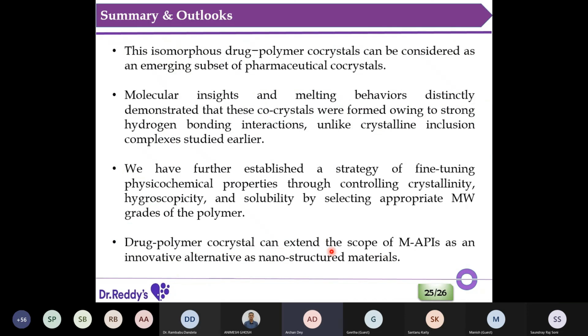Okay, with that I would like to summarize. These isomorphous drug-polymer co-crystals can be considered an emerging subset of pharmaceutical co-crystals. Molecular insights and melting behavior distinctly demonstrated that these co-crystals form owing to strong hydrogen bonding interaction, unlike crystalline inclusion complexes. We have further established a strategy for fine-tuning pharmaceutical physicochemical properties through controlling crystallinity, hygroscopicity and solubility by selecting the appropriate molecular weights and grade for the polymer.